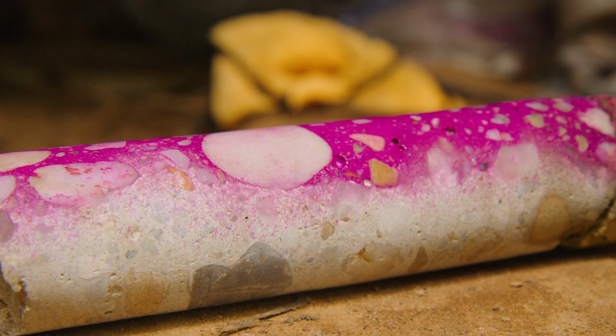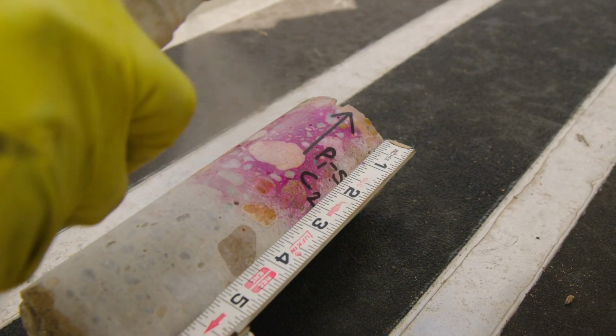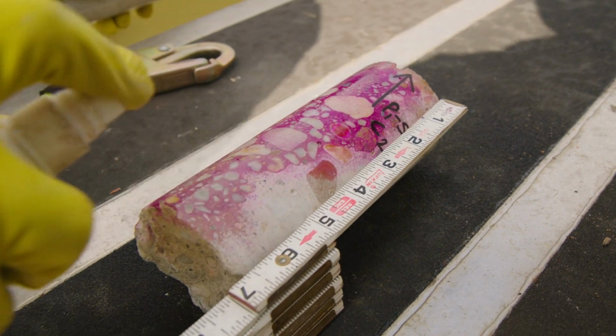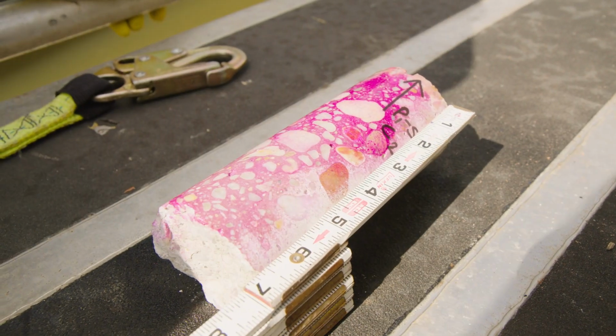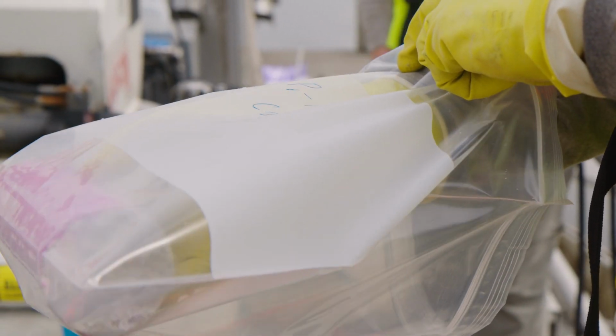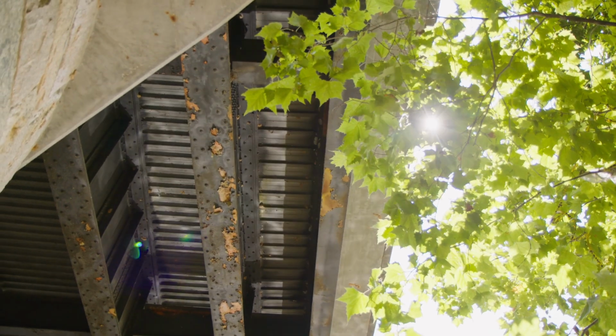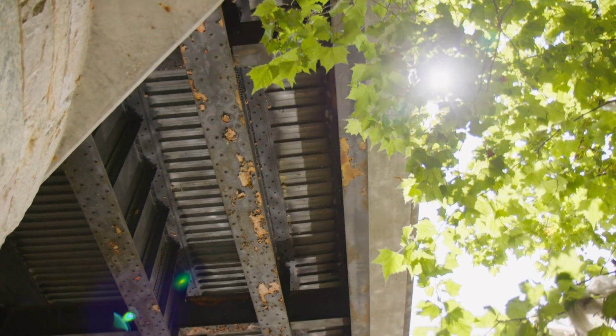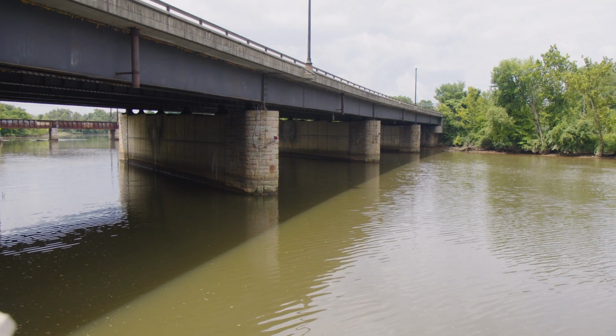The VCS team can identify carbonation immediately on site by spraying an indicator solution onto the sampled cores. The indicator solution changes to a pink or purple color at a pH greater than 9.5, which indicates uncarbonated or alkaline concrete. If the solution is clear, this indicates carbonated concrete. If the carbonation depth reaches the depth of the reinforcement, then corrosion can initiate. Our team determined that corrosion was caused by penetration of chloride ions to the reinforcement depth rather than carbonation.